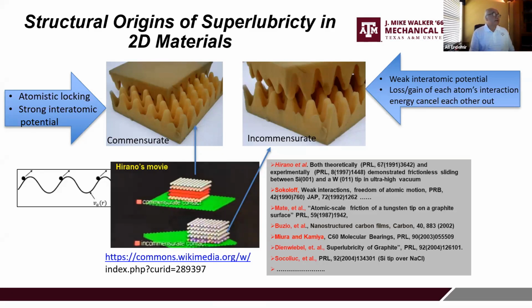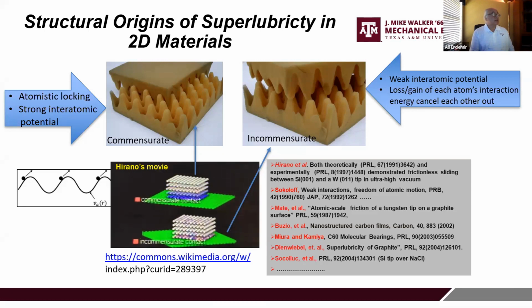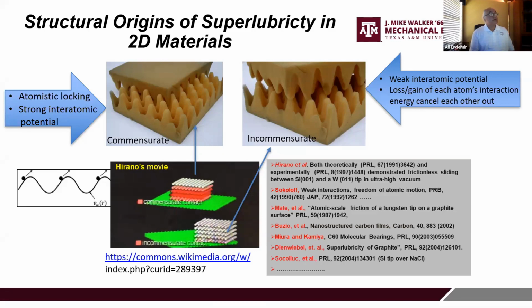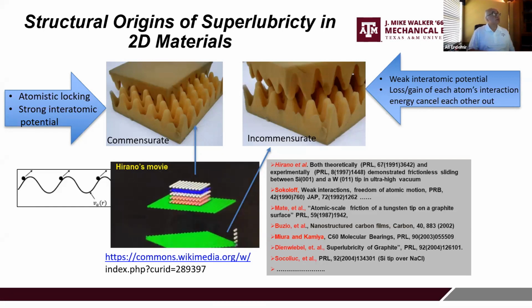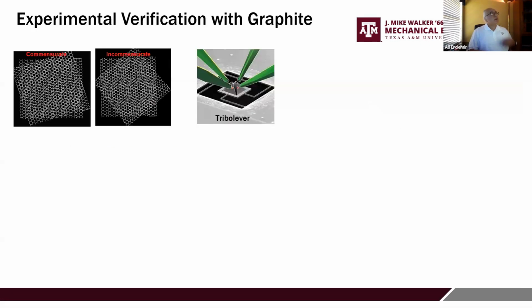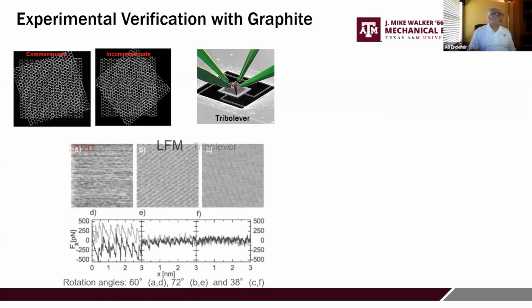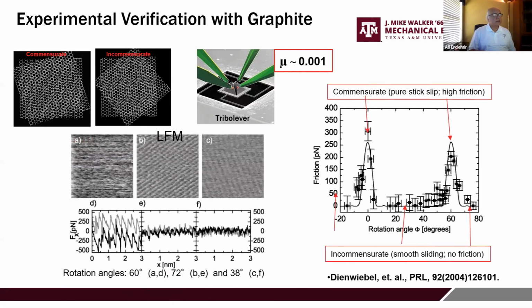of these sliding interfaces, that is, these are physically and structurally a very unique contact configuration. And this, most often, is actually referred to as structural superlubricity. One of the earliest verifications of this was from a group of scientists from Netherlands, especially Dienwiebel and his colleagues in the Netherlands, who actually were able to test this model to see if indeed one can achieve zero friction.